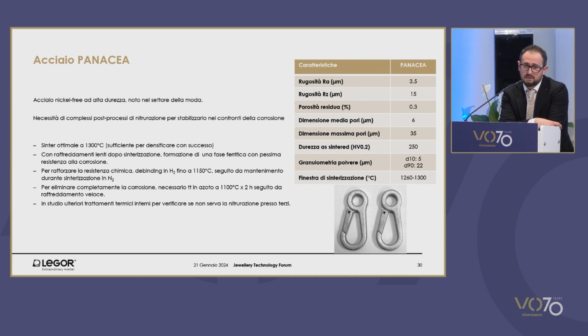We have also investigated steel panacea, which is a nickel-free, much harder steel used in fashion. It has been used, although it has very special characteristics in terms of the risk of obtaining, after sintering, the precipitation in a ferritic phase with very low electrochemical resistance and significant issues of corrosion, which would mean worsening the aesthetic characteristics.